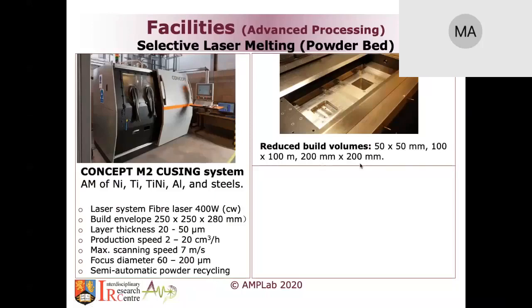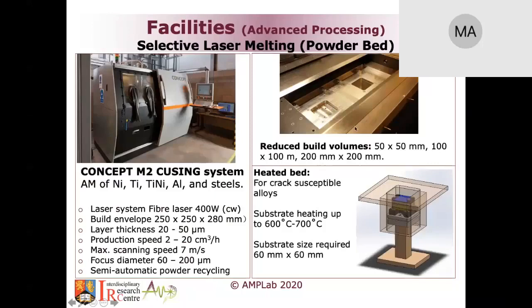We also modified it by having a heated substrate. So we added cartridge heaters into the substrate. Now we can heat the substrate up to 600, 700 degrees. But when we do this, the heated region is only around 60 by 60 millimeter. We cannot really heat the entire substrate. Only a very small section can be heated during the process.